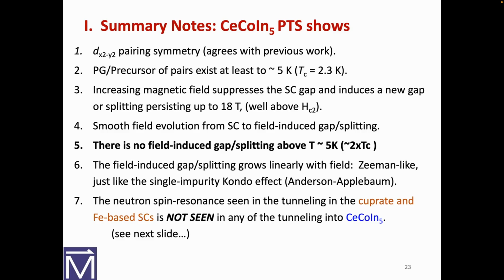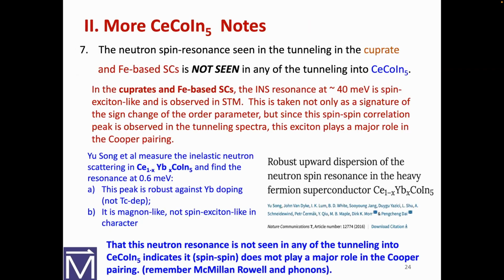So this is something like the neutron spin resonance seen in the cuprates. When I started talking about this, everyone said, how could you say it's Kondo scattering when we know d-wave means spin-spin correlation? And my argument is no. Knowing the order parameter symmetry doesn't tell you anything about the mechanism. It just tells you the order parameter symmetry. So this went on for a while, and I just want to remind you that the spin-spin correlations are not seen. There are correlations in inelastic neutron scattering seen in cerium cobalt indium 5, in the ytterbium part, but these things are not seen in the tunneling. If they're not seen in the tunneling, the electrons don't feel them. So what's going on here?